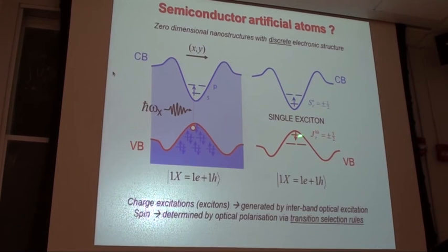And this is pretty important because the confinement in these types of systems, combined with the strain, pushes the light hole band far away, and as a result of that, you can really think about this valence band state as being an orbital state of a discretized heavy hole.